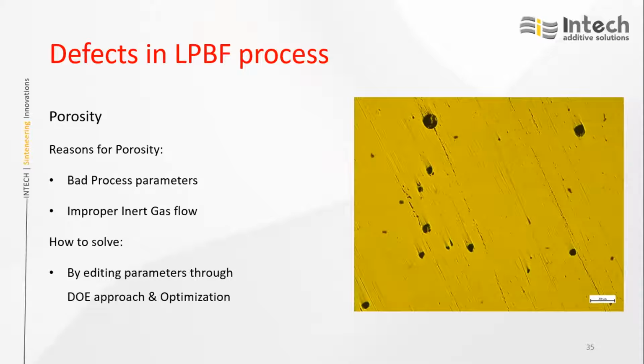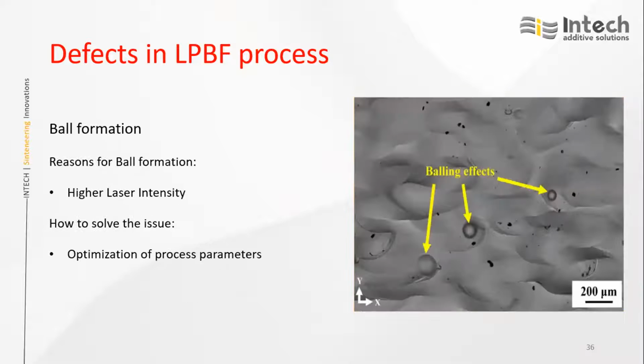Second thing is porosity. Porosity's reasons are also bad process parameters and improper inert gas flow. Bad process parameters is a direct thing. Improper inert gas flow, as I mentioned, the condensate which is generating, if it falls back onto the powder bed, it will disturb the laser beam. When the laser beam interacts with the powder, if this condensate is there, the penetration of the laser beam to the required depth will not happen. Because of this, the porosity may come. So again, by optimizing the process parameters and controlling the inert gas flow, the porosity can be controlled.